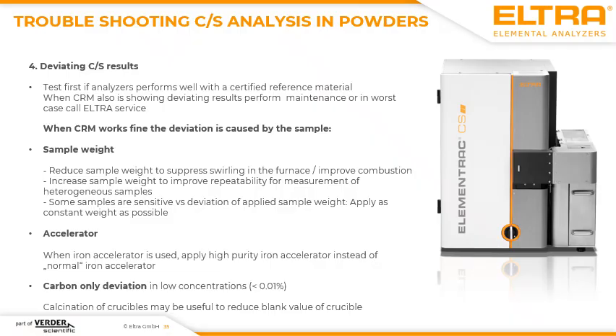It could also mean that deviating results are caused by, I would say, very varying sample weights. When you have, for example, a finely divided dust, you cannot apply in the first measurement 50 milligrams, in the second measurement, for example, 150 milligrams. That could cause a big irritation in the analyzer. So when possible, provide very homogeneous sample weights like, for example, 50 milligrams plus minus 10 milligrams.